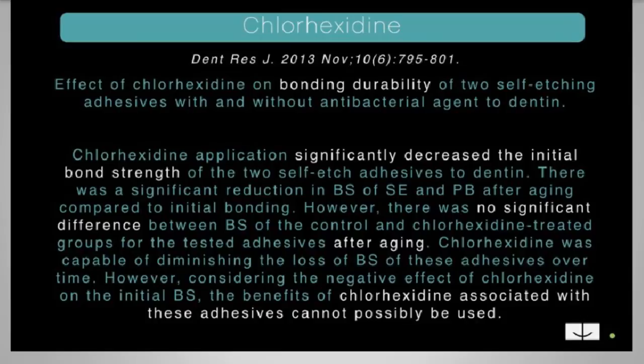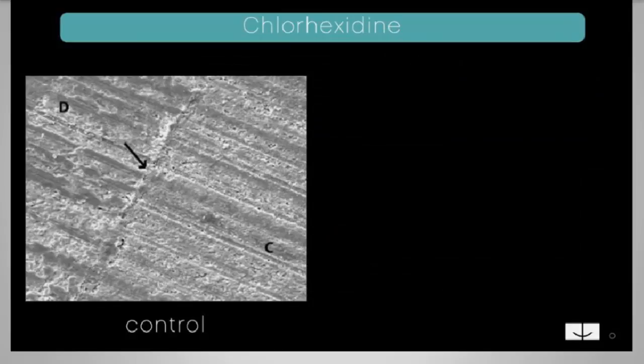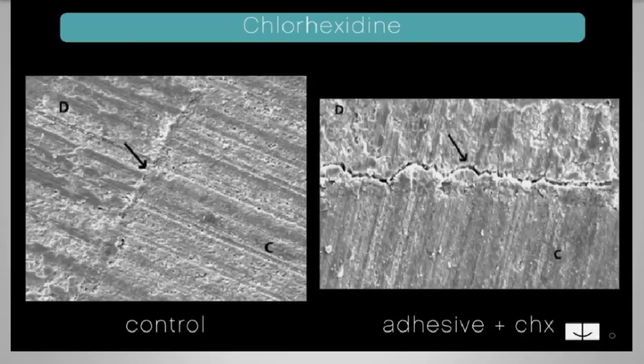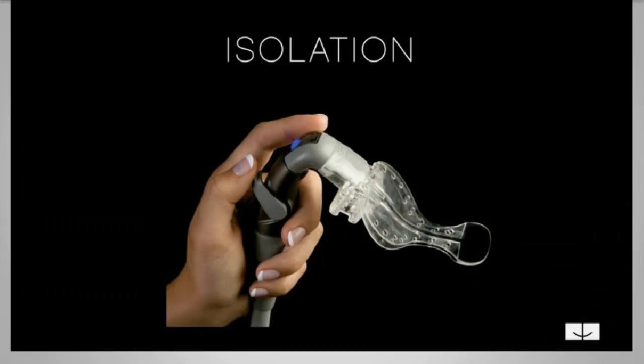Now they found after aging, after a long time, the bond strengths came back. But chlorhexidine associated with these self-etching adhesives shouldn't really be used. Here are very interesting photos about that. Here's the control without any chlorhexidine and self-etch adhesives. And here is a picture with chlorhexidine pre-treatment and then your self-etching adhesive. And you can see that breakdown there. So if this is a non-retentive crown prep that you're going to bond in the mouth, I would not use chlorhexidine before using a self-etching adhesive. All right, really good point there.